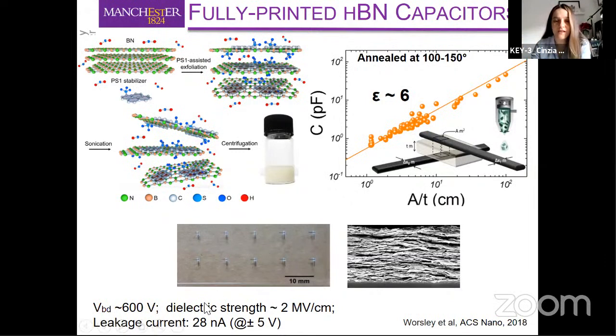And if you look at the numbers that are reported down here, you will see that actually from a dielectric point of view, this boron nitride ink is extremely good. It's quite comparable to silicon oxide. And so it can be used as a dielectric for devices. And not only within 2D materials-based electronics, but more in general, we can also use it in combination with other nanomaterials or with other technologies. And I will show you 2 examples of what I mean.